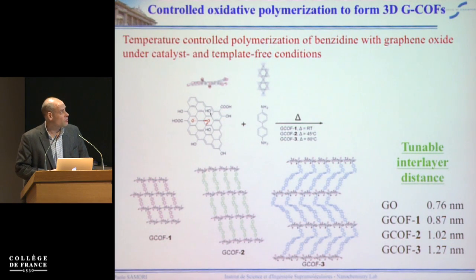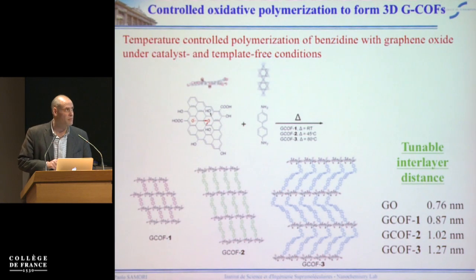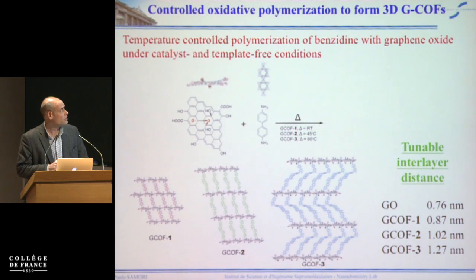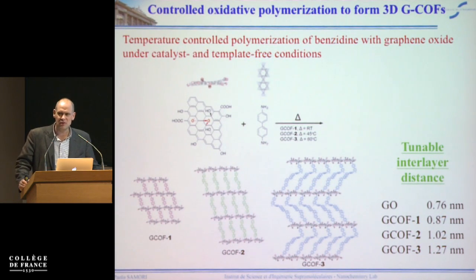If you want to grow vertically to the basal plane of the graphene, you have to do a chemistry where you put in pillars that interact with the only functional groups on the basal plane, and these are the epoxide groups. The chemistry we performed is a pretty simple one that is already known, a ring-opening reaction with an amino-functionalized unit. The novelty of our approach compared to what you can find already in the literature is that we decided to play with a building block that is benzidine, which is known to undergo oligomerization or polymerization if exposed to mild temperature.